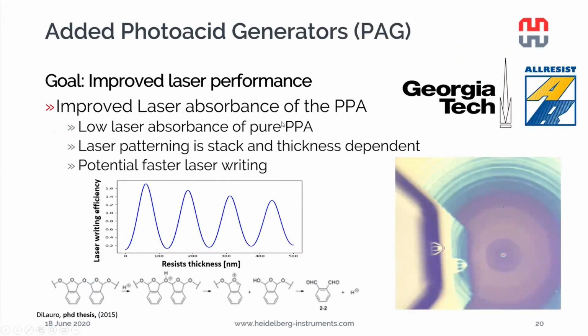The laser writer is quite a new product, and I think my colleague Simon talked about this recently. One of the current issues with the laser writer is that the PPA doesn't absorb a lot of this laser power. It's quite transparent, and we get some interference effects in the film itself. Therefore, the laser absorption depends on the thickness of the film. So if you have a resist thickness of 120 nanometers, we get a low absorbance. If you have one of just 60 nanometers or 180 nanometers, we get a high absorption. This is a bit tricky, as we always have to simulate the sample or fine-tune the laser parameters, and we would like to be independent of the resist thickness.